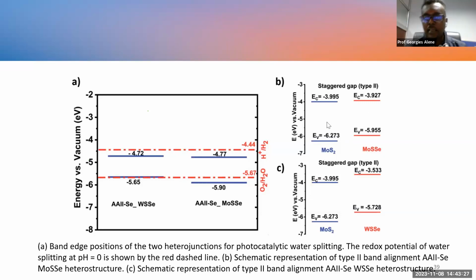And the other thing is we plot together for the two monolayers, that means the MoSSe and MoS2, for example, and we put it together. And when you put the band edges together in a plot, and when you get this staggered gap, then it is called type 2 band gap alignment.